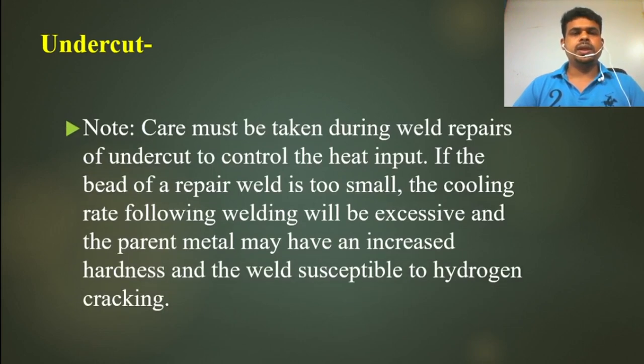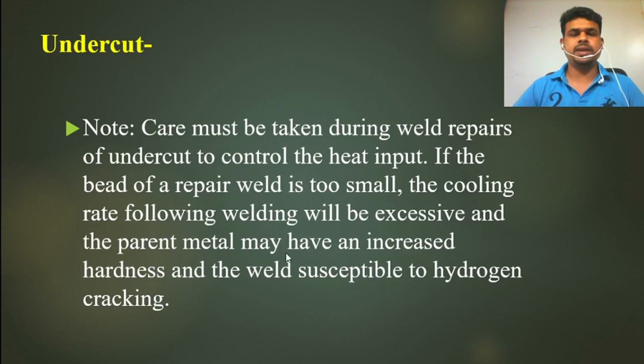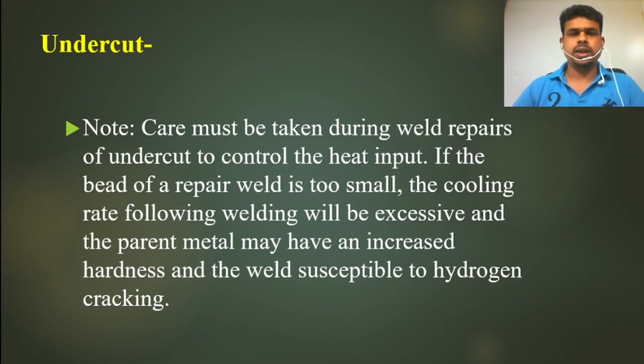We need to note that care must be taken during welding repairs of undercut to control the heat. If the bead of a repair weld is too small, the cooling rate becomes excessive and the weld may have increased hardness, making the weld susceptible to hydrogen cracking. To avoid increasing hardness and hydrogen cracking, we must control the heat carefully when performing weld repairs.